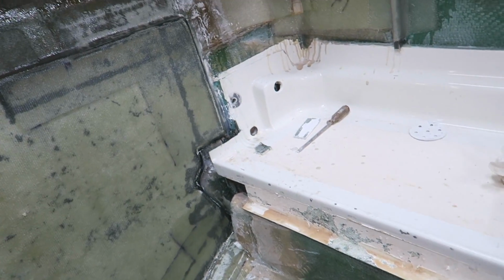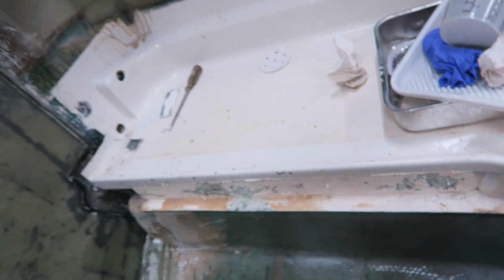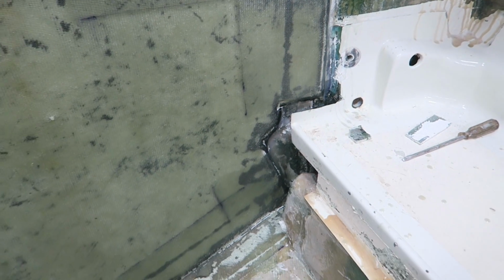Most inner skins usually average around 1/8, and then your bulk tends to be more on the exterior part of the laminate. And I can see that there's some little oopsies here and there that I'm going to have to come back and sand and kind of touch up, but nothing major. I would say this is probably the worst of it. I must have had a little chunk of something on the back side of this 4th layer of fiberglass that just, well, it got embedded into the transom.